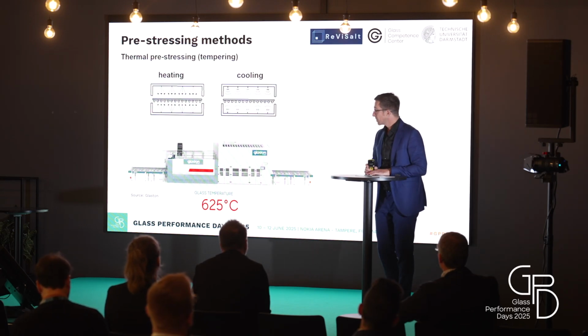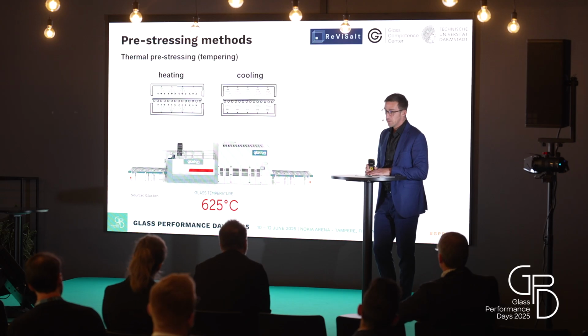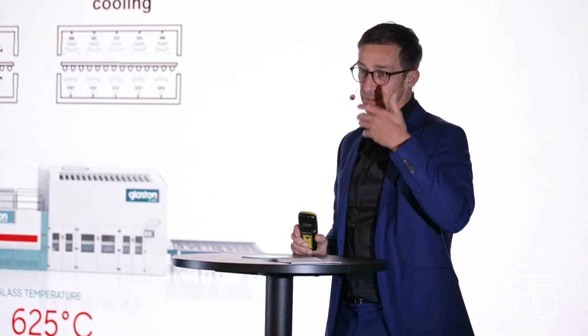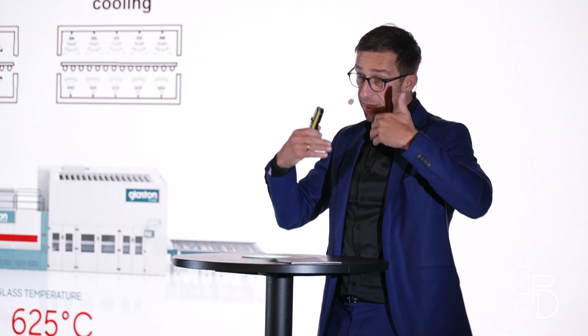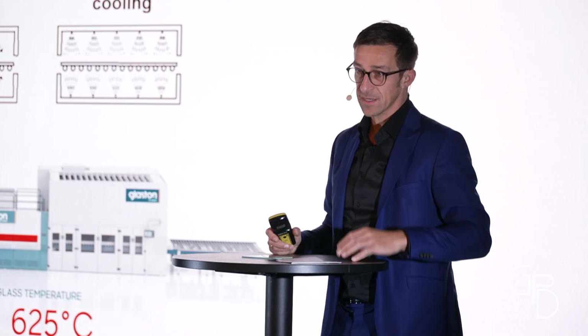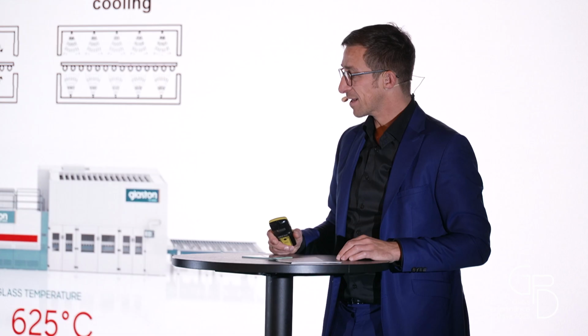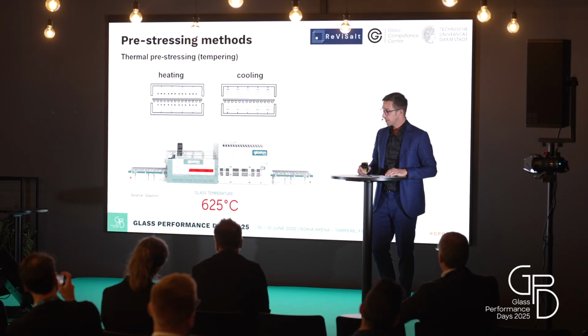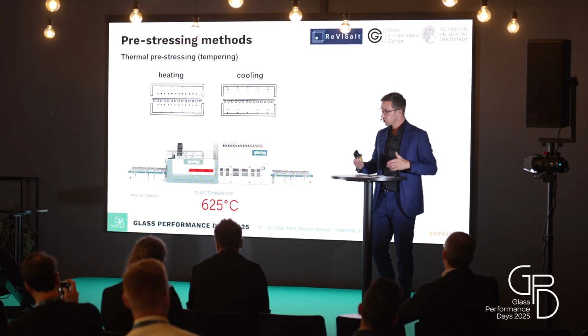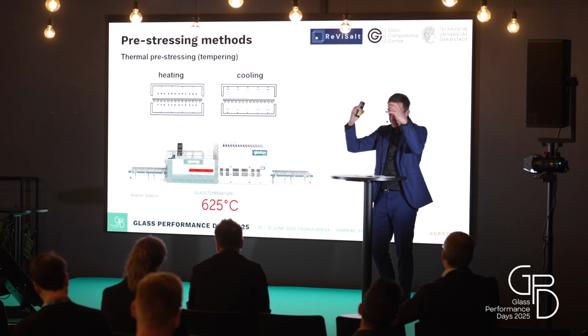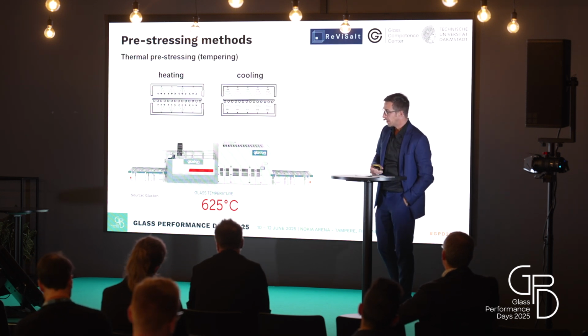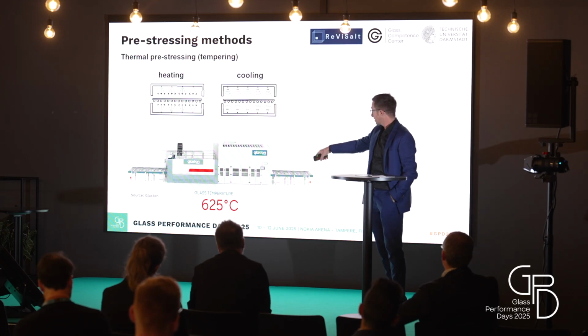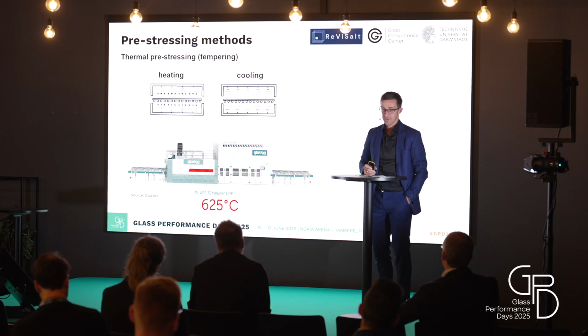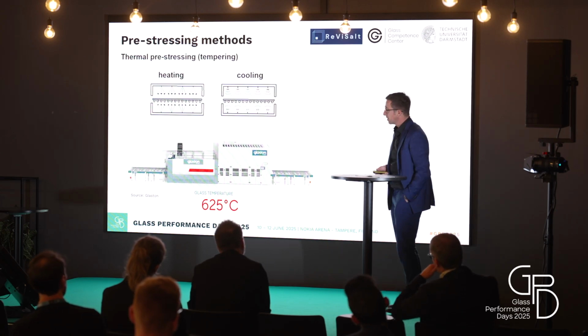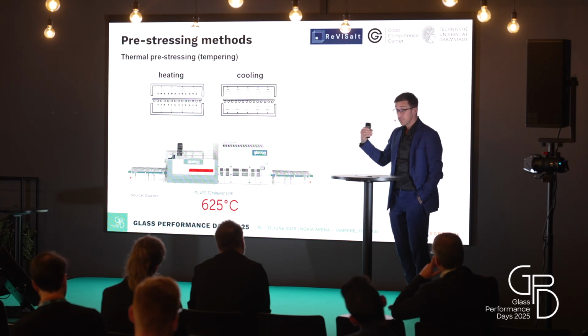Now I want to talk about the typical methods, how we can pre-stress the glass. I think you know the thermal tempering process or pre-stressing. We do some pre-processing, we cut the glass, we clean the glass, we grind it and so on. Then we bring it in the furnace, heat it up. It depends a little bit on the thickness and whether there is a coating on the glass surface. We heat it up in a few minutes, then we do a rapid cooling in the quench, and then we save the energy inside the glass, and we have tension in the core and compression at the surface. We heat up the glass to a range of 630 degrees, more or less. It depends a little bit. Okay, cool industry process. It works very well.